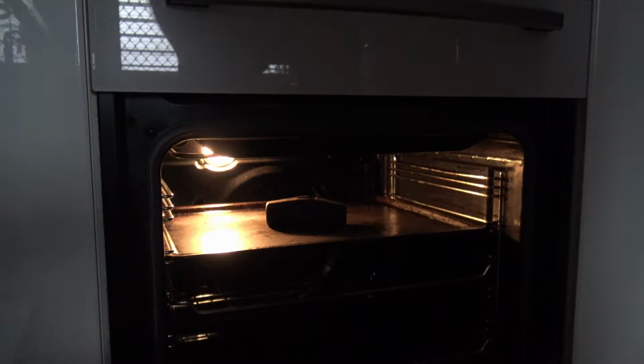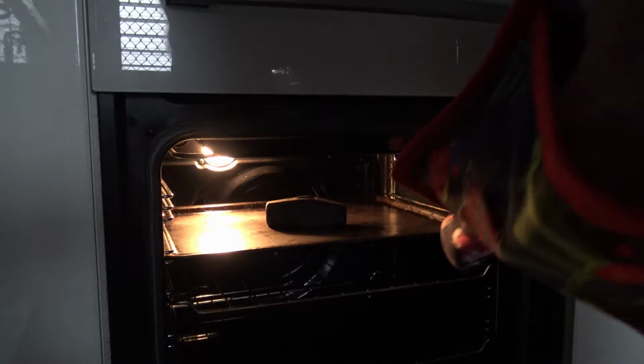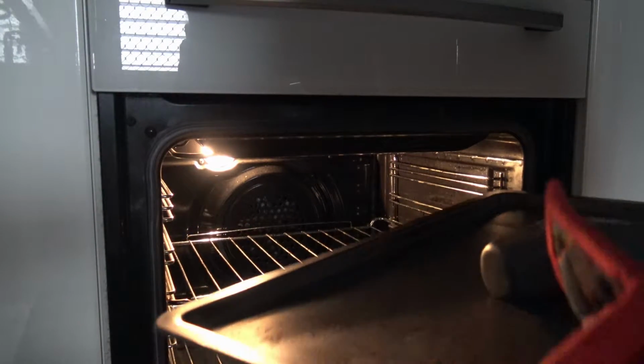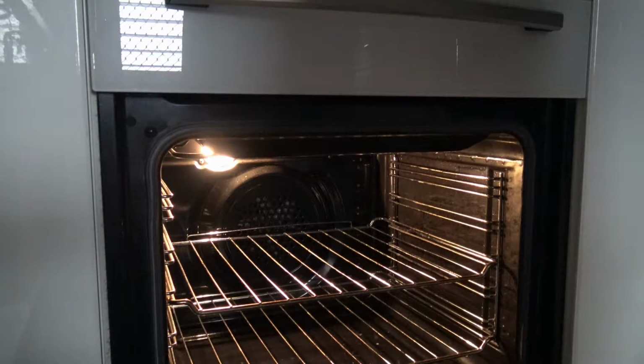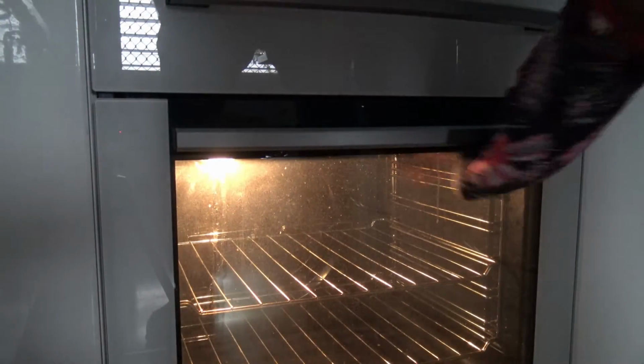I'm aiming for a temperature of 230 degrees Celsius, or about 450 degrees Fahrenheit, and I give it time to warm up to that temperature and then hold it there for an hour. Nicely baked, I take the hammerhead out of the oven and again quench it in water.